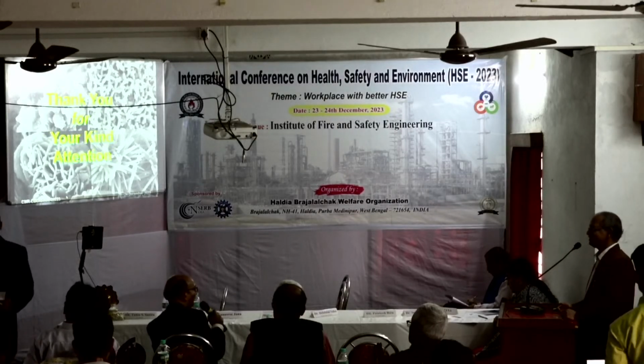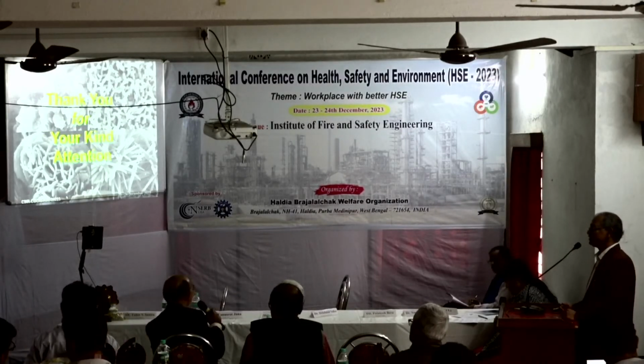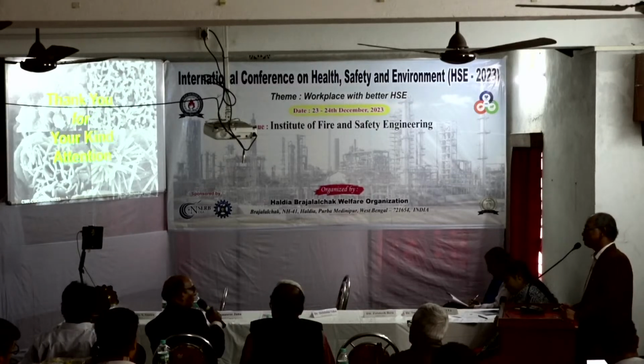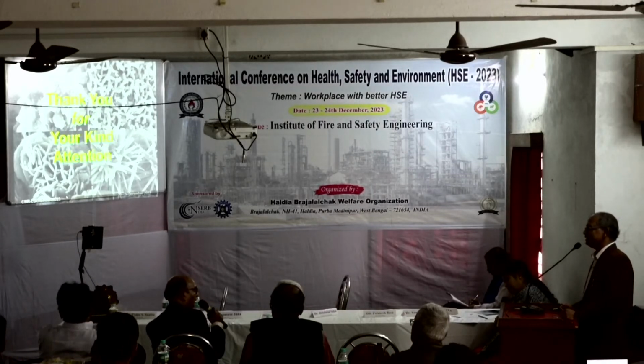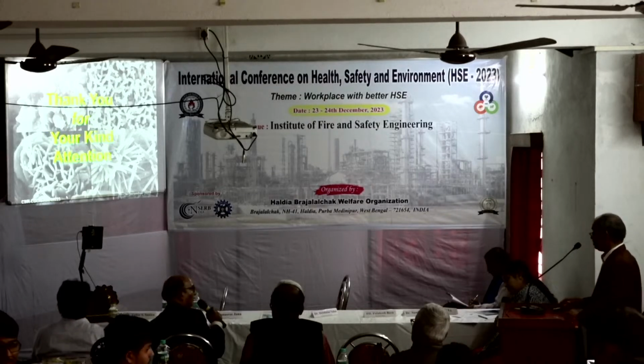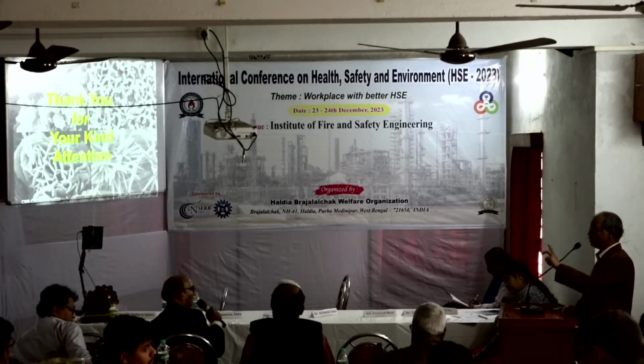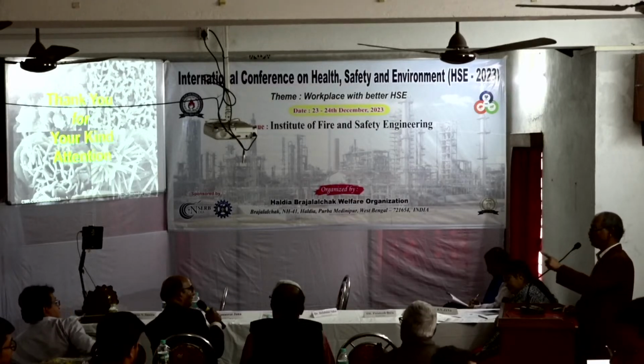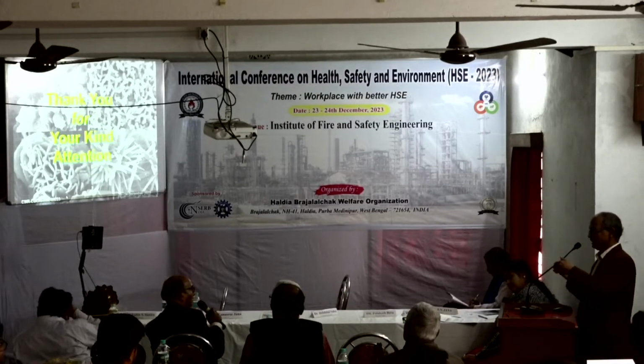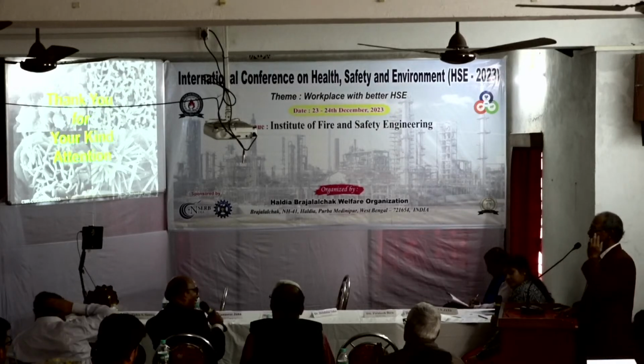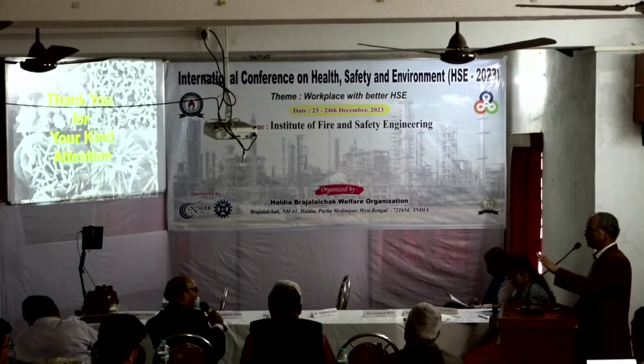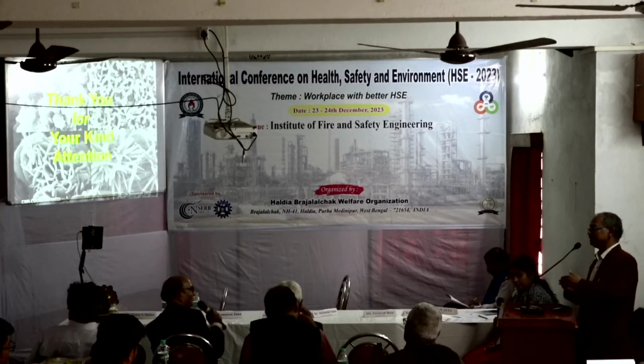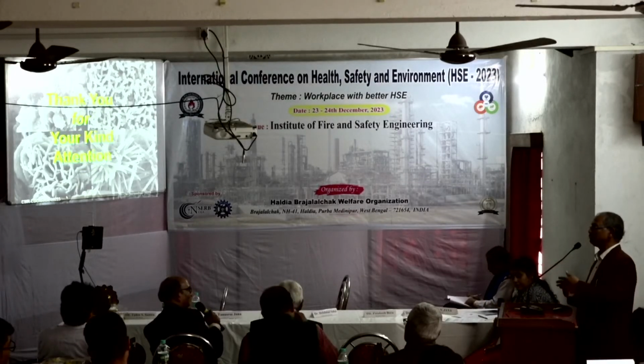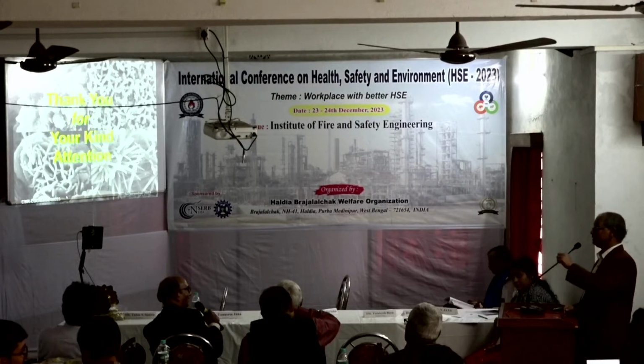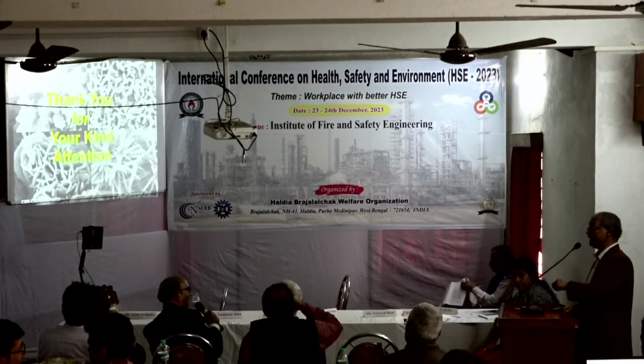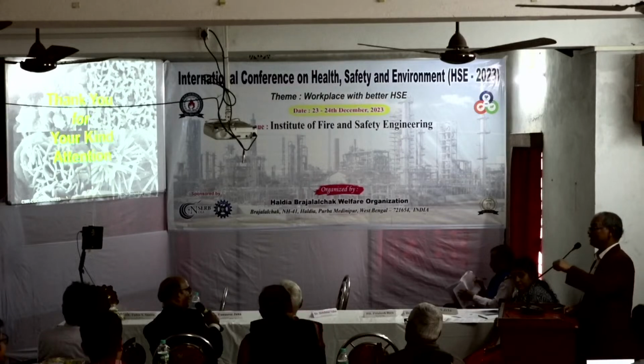That's all I'm saying. So, another question is, anti-reflection and hydrophobic, both at the same time, right? Hydrophobic coating and anti-reflection. No, I have shown 2 layers. One is anti-reflection and another is hydrophobic. The hydrophobic surface is not anti-reflection. What we have done, we have first deposited the anti-reflection coating, over which we deposited the hydrophobic coating, maintaining the refractive index and thickness which is desired to keep the anti-reflection property constant.